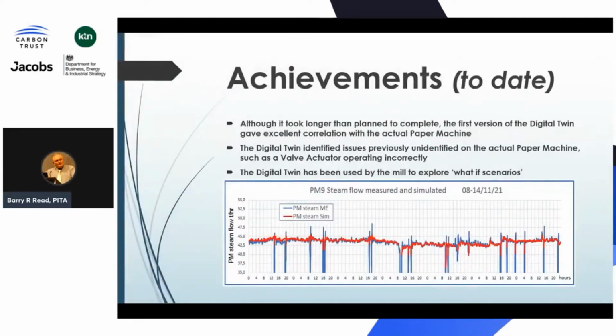Okay, so the achievements to date. It took a lot longer to complete than anticipated due to COVID-19, and nearly 600 days elapsed from our first meeting on site to our second meeting on site. But we got there, and as you can see from the graph at the bottom of the page, the results of the simulation and the measured results are exceedingly good. The mill were very impressed by the correlation between the two.